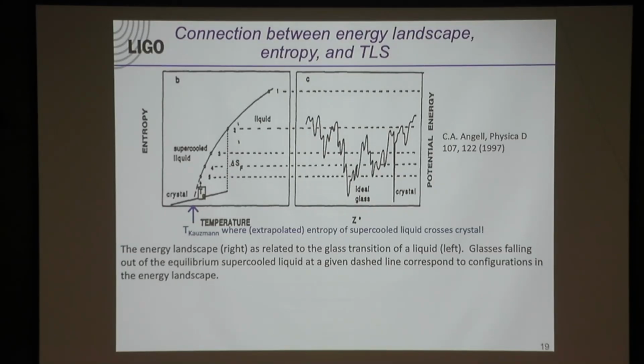So it is a remarkable statement, and one of the big points I hope to leave you with, that amorphous materials are not crystalline, but they have their own underlying order. It's a short range order, a medium range order, not long range order, but it's also not nanocrystalline. Nanocrystalline is actually quite a bit higher in the energy landscape because of disorder at the boundaries. But it is a very ordered state in its own way. And that low entropy,